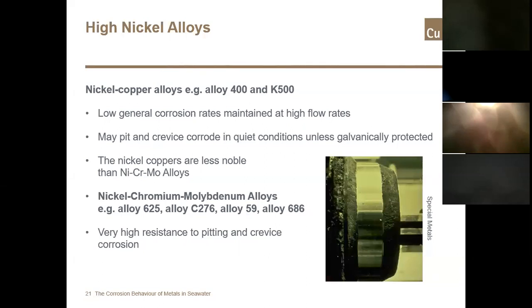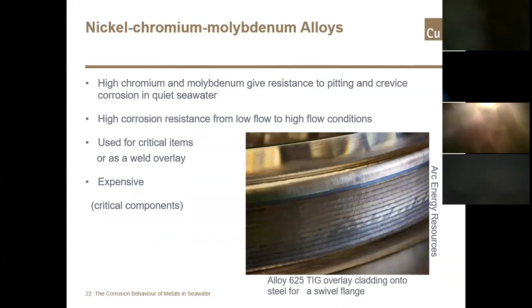The alloys are typically used for fasteners, shafting, pumps, valve components, etc. And cast versions are available for impellers. The other significant group of nickel alloys, as just mentioned, was the nickel chromium molybdenum alloys. And these offer a very high resistance to corrosion, and in particular pitting and crevice corrosion. They've got a high corrosion resistance in both low and high flowing conditions, and they can be used for critical items.